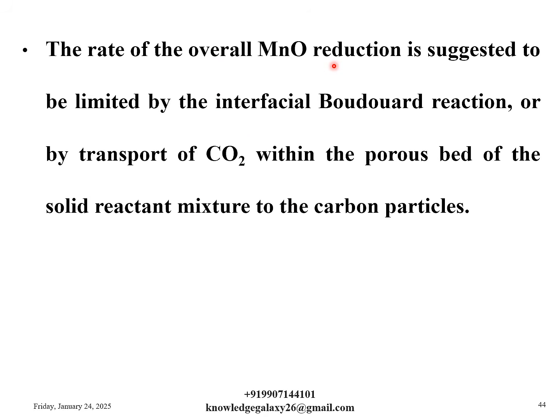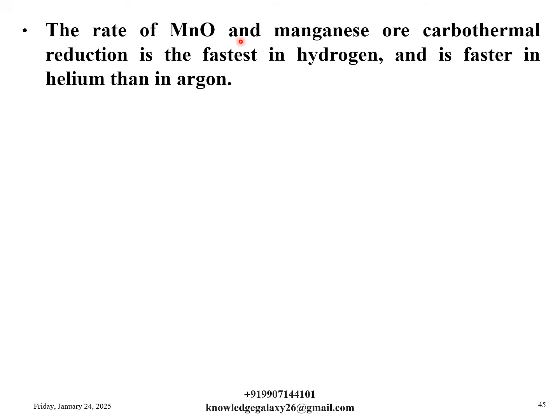The rate of the overall MnO reduction is suggested to be limited by the interfacial Boudouard reaction or by transport of CO2 within the porous bed of the solid reactant mixture to the carbon particles. At high temperatures, when MnO is reduced from the molten slag, direct graphite molten slag reaction may dominate in the reduction processes. The rate of MnO and manganese ore carbothermal reduction is the fastest in hydrogen and is faster in helium than in argon.